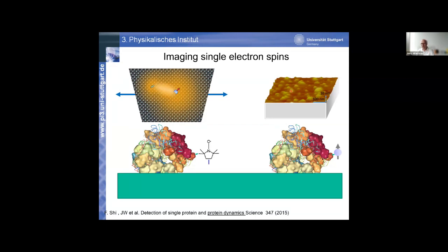And our interpretation is that these are individual proteins with single electron spins. The scale bar here is 100 nanometers. That gives you roughly an idea of the spatial resolution. So you can use this technique to localize these electron spins. But you can do more than this, and this is what I would like to allude to.